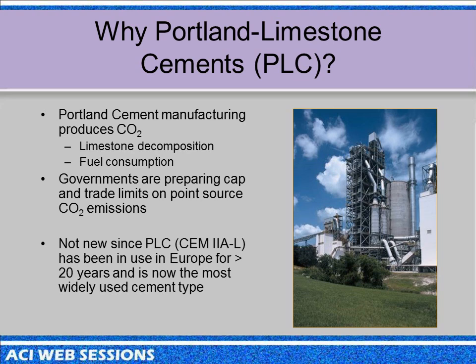So if they can take some of that raw limestone and intergrind it when they grind the clinker to cement powder and make a technical cement that works, they can reduce their point source emission of CO2 by the amount of clinker they reduce in that mix. So that's where the premise for this comes from.